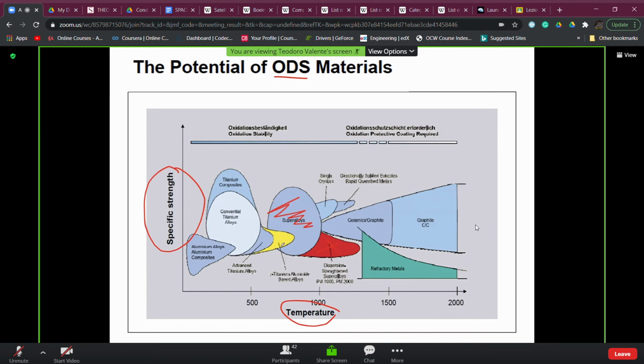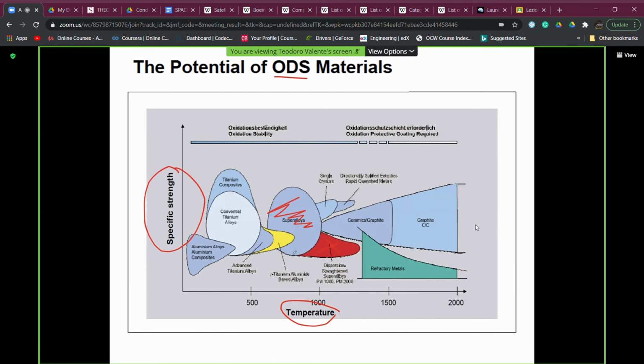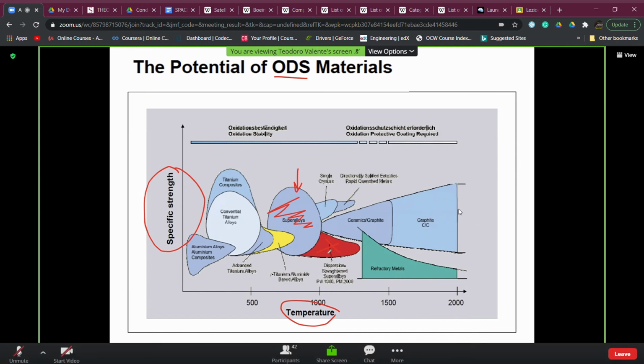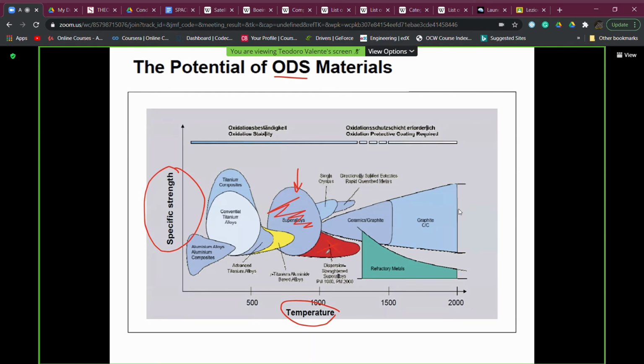Even though they are positioned more or less at the lower level of specific strength when compared with nickel-based superalloys, for which the original idea was to use the ODS materials as substitutes, we can observe a higher allowed working temperature, in some cases up to 1300 Celsius. So what is expected from this class of materials is a higher resistance to high temperature and higher resistance to corrosion.